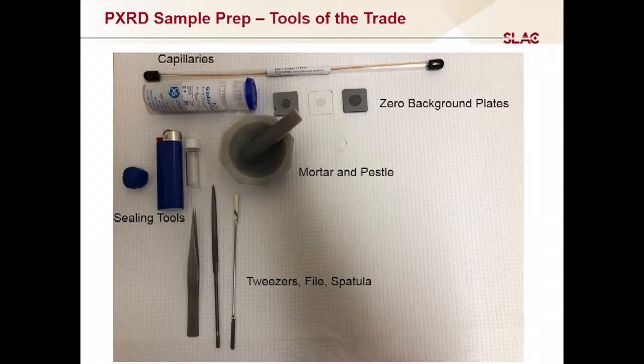So the surface should be flat and as smooth as you can make it. And that's actually a very tricky bit, because the easiest way to make a nice, flat, smooth surface is to take something like a microscope slide and just smash it down on the top of your powder. And this will give you a very nice surface, but it's also about the worst thing you can possibly do in mounting a powder sample because it's almost guaranteed to give you some preferred orientation. So if your crystallites are not essentially spherical, if they have any kind of shape to them, smashing them down will cause them to orient.